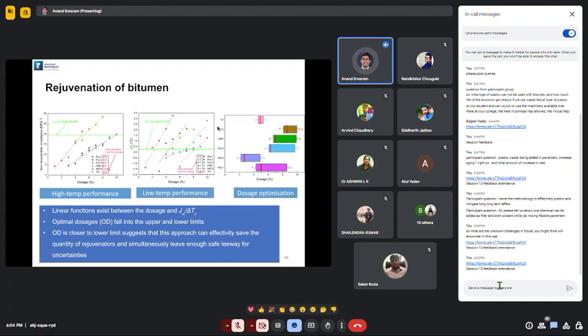So that's what I've talked about here. We try to manage the high temperature performance, we try to manage the low temperature performance, and then we try to optimize these dosages. The optimal dosage is often closer to the lower limit, which suggests that this fitting algorithm-based approach can also save the quantity of rejuvenators, and also leave sufficient leeway for accommodating uncertainties and so on.